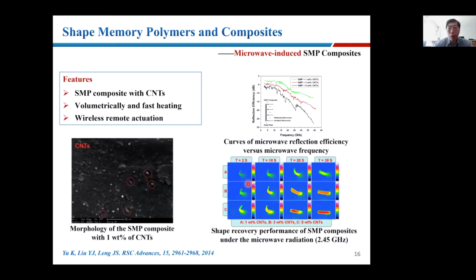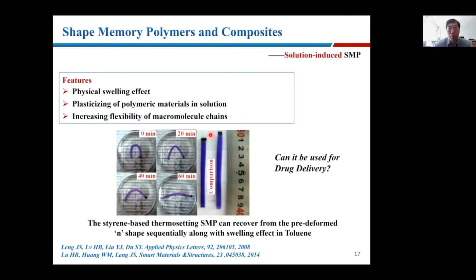So we also try microwave. The reason is microwave can be absorbed by the shape memory polymer, by nanotubes, and also this one can do faster heating and wireless control and remote control. So you can see from 2 seconds to 30 seconds, the sample can deploy by microwave with different percentages of carbon nanotube inside the shape memory polymer.